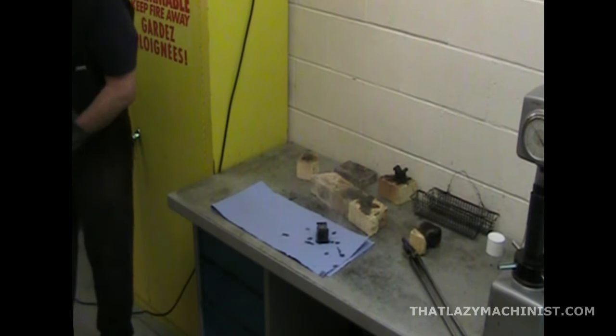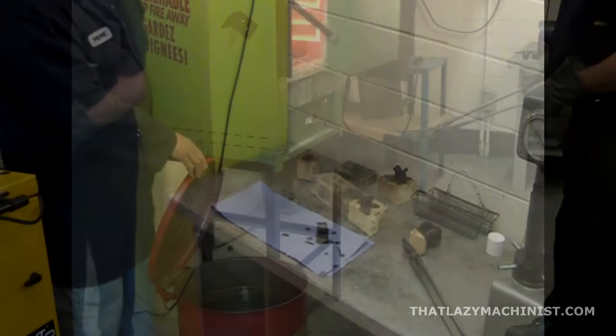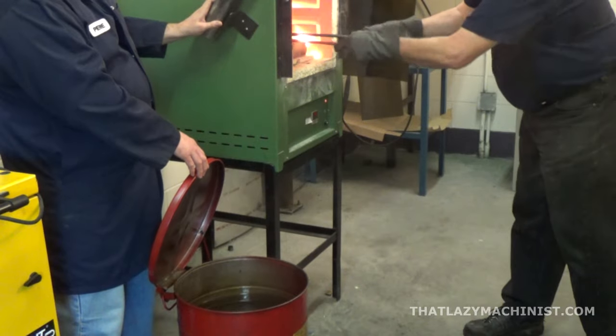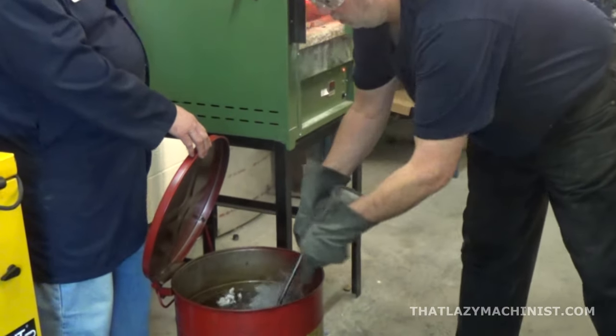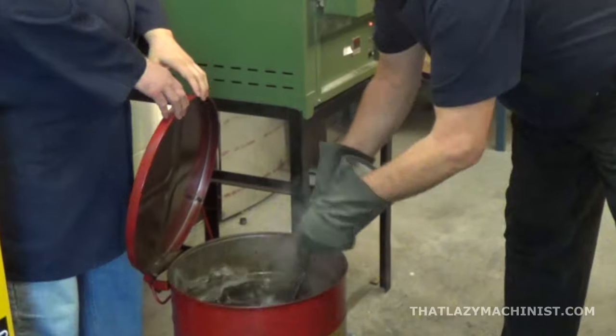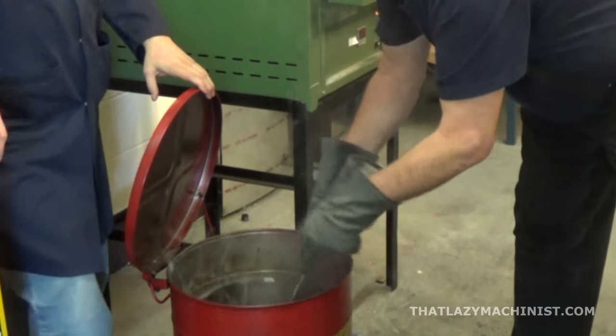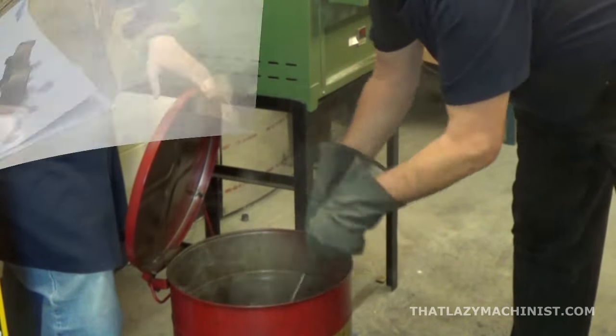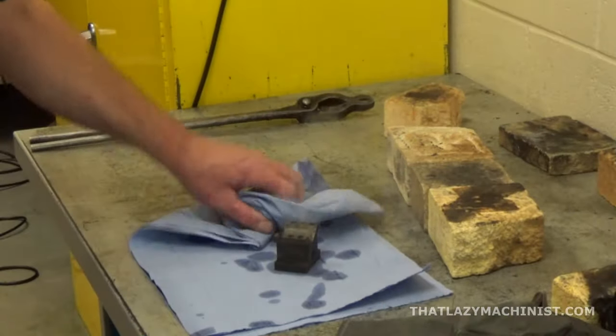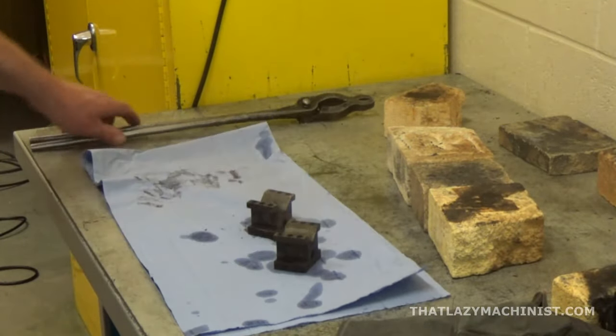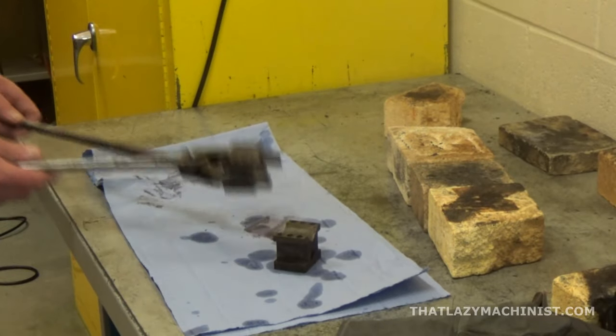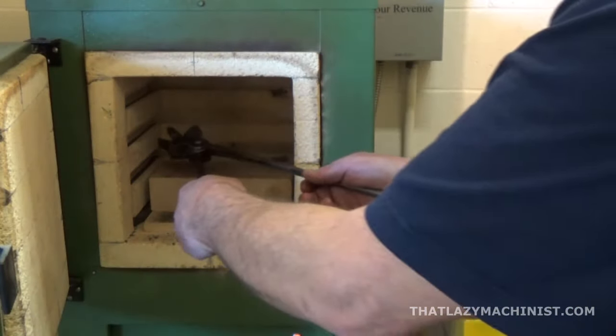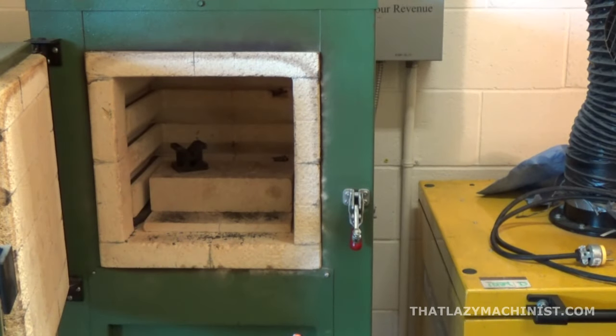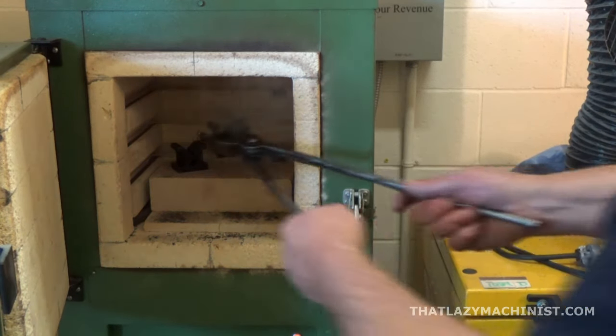Note that I'm pulling the parts from the oil before they cool down completely. I'm pulling them when they're somewhere around 400-450 degrees. Now this is important to reduce the chances of the part cracking before they make it to the tempering oven. And in order to avoid smoking out the whole shop, remove the excess oil from the blocks before inserting into the tempering oven.